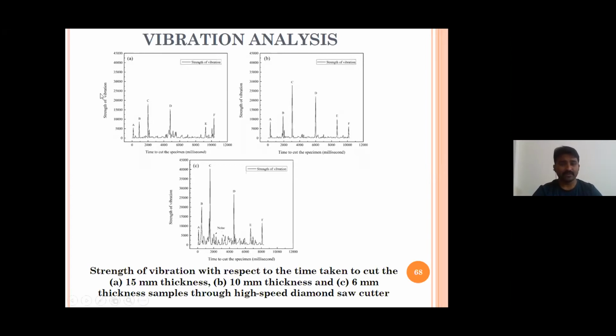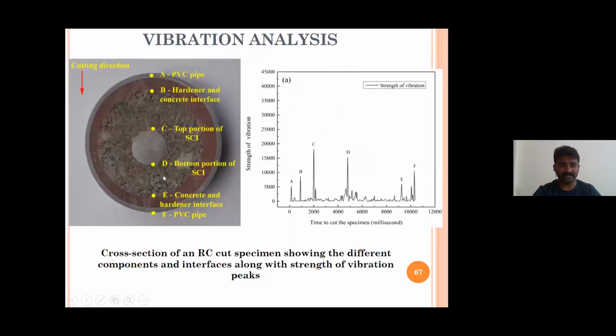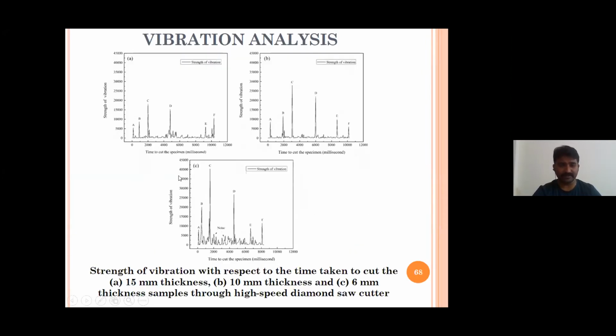Okay. So for part A, 15 mm thick samples, these are the strength of vibration values at A, B, C, D, E, F points. These are A, B, C, D, E, F points at different interfaces. See, the strength of vibration for 15 mm samples is slightly lesser compared to 10 mm. For 10 mm, there is a sudden increase at the steel concrete interface here, and even in A, B, all the points.